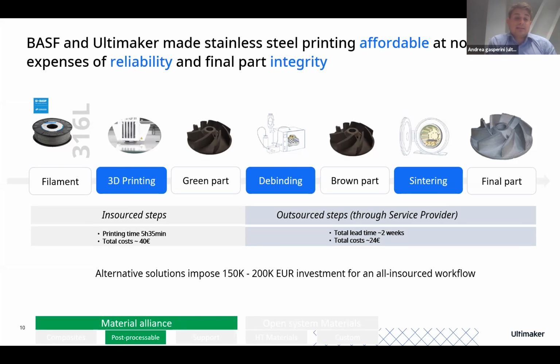And then, as you can see, you only have to perform the printing step, which, for example, for a pump impeller would last 5 hours for a total cost of 40 euros, and you outsource the debinding and sintering steps, and it would take roughly 2 to 3 weeks to be performed with a total cost of 24 euros. Therefore, you're going to get your final part, a pump impeller that I have here in my hands, for the cost of 64 euros total versus the 1,000 euros that you normally would pay for such a part as a spare part.